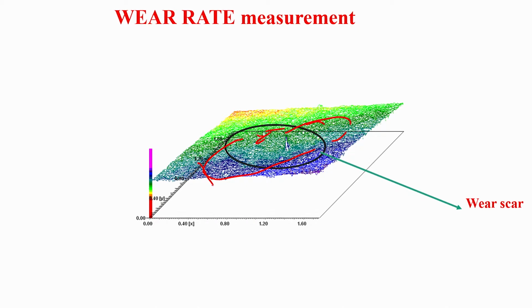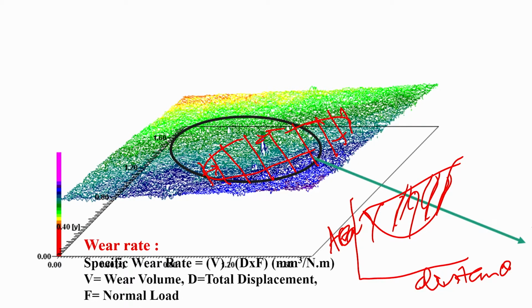I have mentioned in one of the earlier lectures that what you do is take the various 2D profiles at various spatial locations on the wear scar, and then you plot the area of each profile as a function of distance. Then you get this kind of a curve, and you take the area under the curve to get the volume, and this volume is the wear volume.